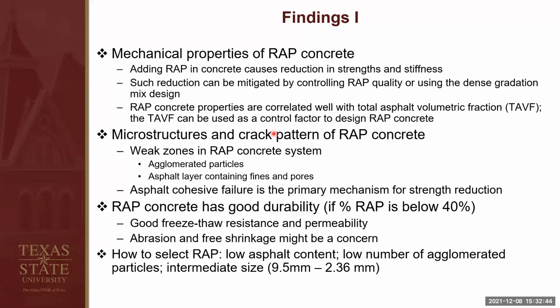So first of all, we want to control the asphalt content. We want to select RAP which has the lowest asphalt content as possible. We also want to limit the number of agglomerated particles. And we also think the gradation of the RAP is very important. We like intermediate particle sized RAP. Our ideal particle size is 9.5 millimeter to 2.36 millimeter. So within this size range, the RAP is likely to have very low amount of agglomerated particles. And also this intermediate size can help us design dense graded RAP concrete, which will have very low strength reduction.